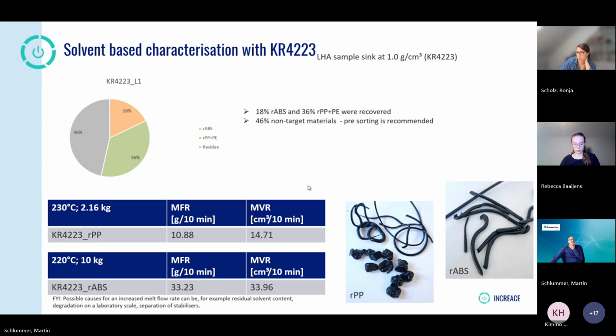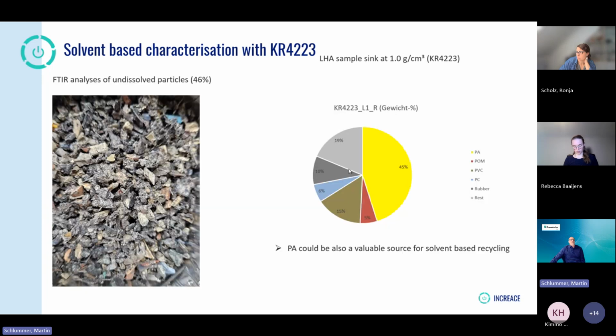For the solvent-based recycling, even from these shares, we were able to recover 18% of recycled ABS and 36% of recycled polypropylene and polyethylene. The outcome from this was still quite nice for us. The ABS here is still at lab scale, not too good in drying, a bit worse, so the level is still a bit too high. But for the polypropylene, it is still sufficient and working quite well.